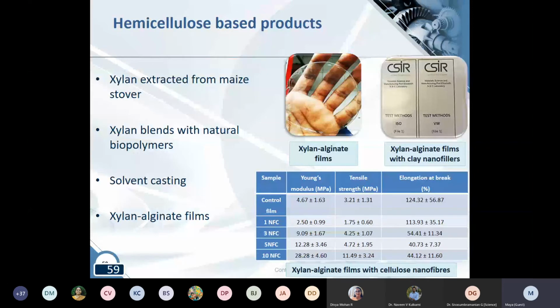I think the biopolymer that he chose was alginate, which, as you know, can be obtained from seaweed as well. And the films are formed by solvent casting technique, and films were also formed by adding clay as well as cellulose nanofibers. And I think for the films which contain cellulose nanofibers, we noticed improved strength and modulus. And this was mainly attributed to the interfibrillar network in cellulose nanofibers. Now, xylan also has applications in the packaging sector, especially it can be used for development of edible packaging films.